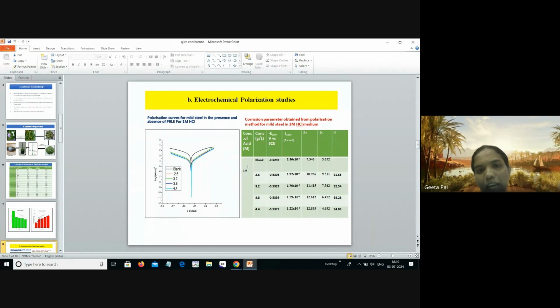It indicates that on the cathodic side, there is evolution of hydrogen gas. On the anodic side, there is dissolution of the metal plates. Whereas in the case of the blank solution, or in the presence of 1 molar HCl solution, both metal dissolution as well as hydrogen gas evolution are comparatively high. That is indicated by the high current density value in the case of the blank solution. As the inhibitor concentration increases, the corrosion current density value decreases.